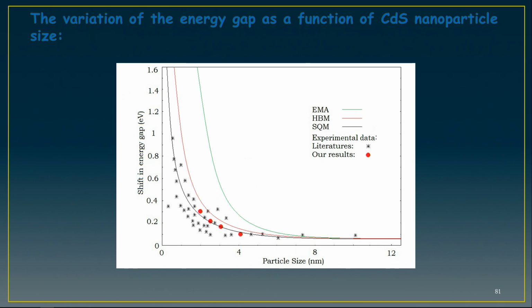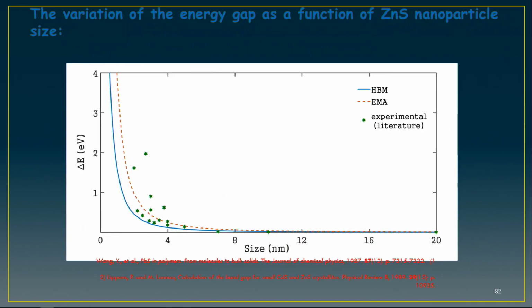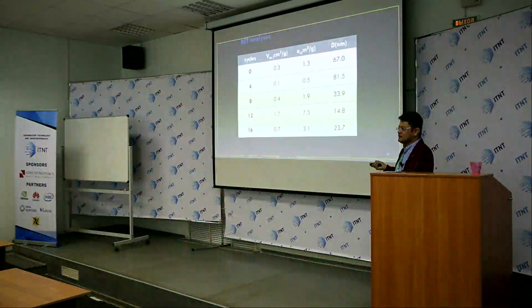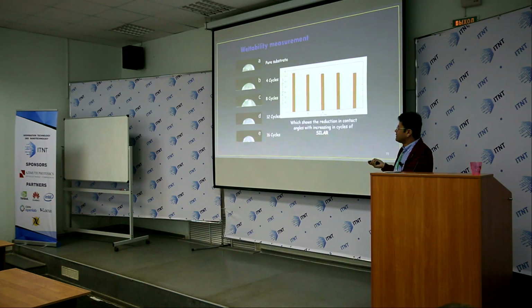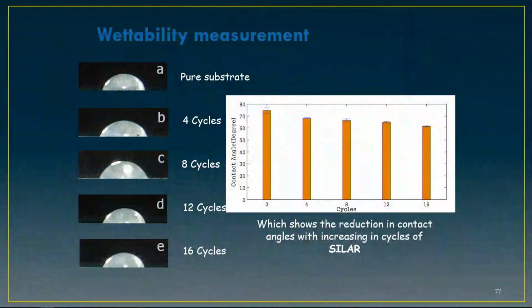In the case of other materials, zinc sulfide materials, we have also checked these properties. And we also have some other experiments on the surface. Maybe it will be interesting for Professor Sajin: the wettability and contact angle measurements on different surfaces, by changing the morphology of the surfaces and also the chemical components of the surfaces.